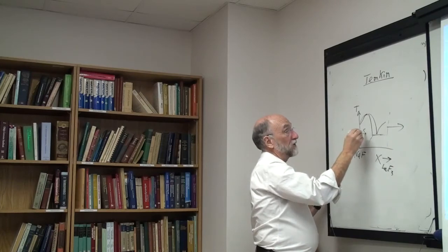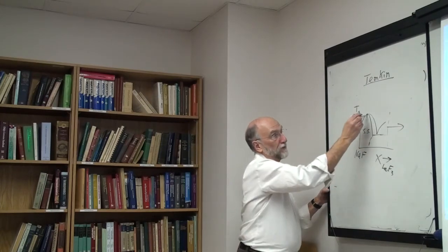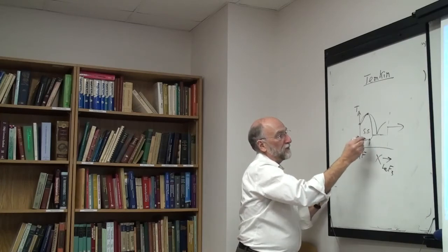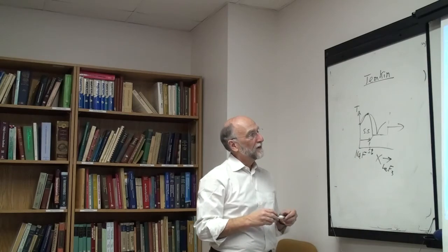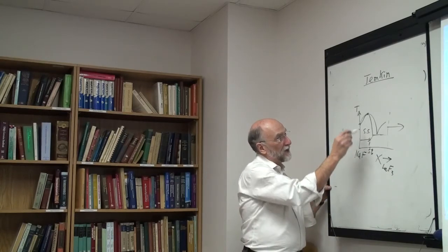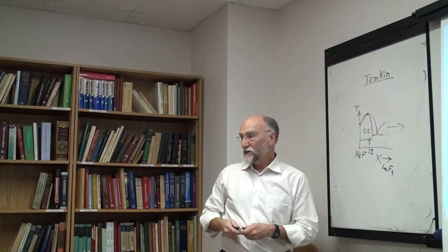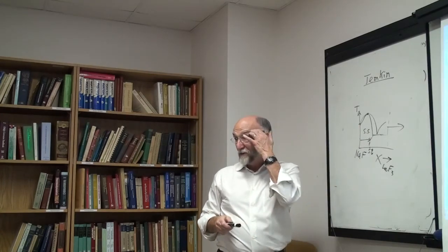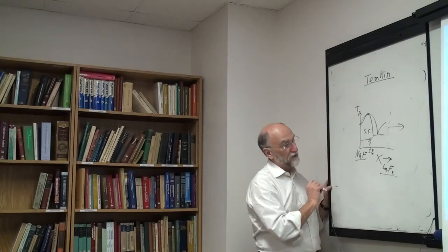But over here you have a solid solution of sodium fluoride and lanthanum fluoride with a maximum. And this solubility is usually only 5% or 3% or something like that. So you have a very narrow solid solution range, 3–5%, but it goes through a maximum. And there are many, many systems like that. It seems to be the rule rather than the exception when this here has a different charge than this.